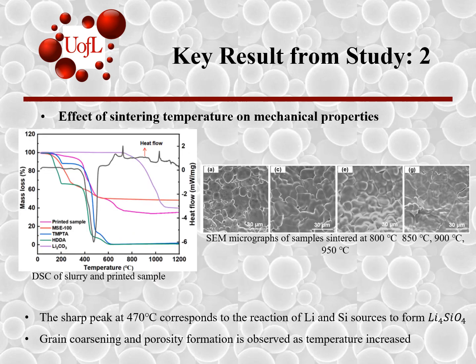This is another result of the study. What's the effect of sintering temperature on the mechanical properties of the final part? On the left we have the DSC-TG curves of the slurry and the printed sample. This test characterizes the thermal behavior. The samples are made to sustain a thermal cycle which makes us understand the mass loss and the exothermic or endothermic heat flow with respect to the material.